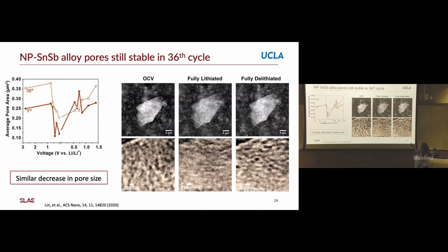And you can also look at the pores, and still we're seeing the filling in of pores when we lithiate and the pores reappearing when we delithiate. So it seems to be cycling really, really well and really stably.